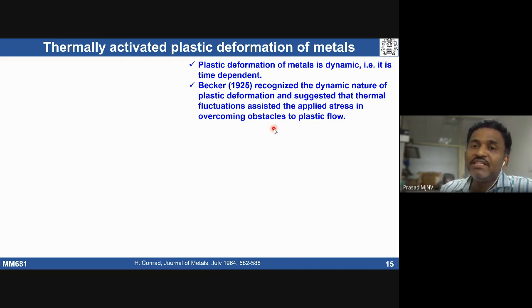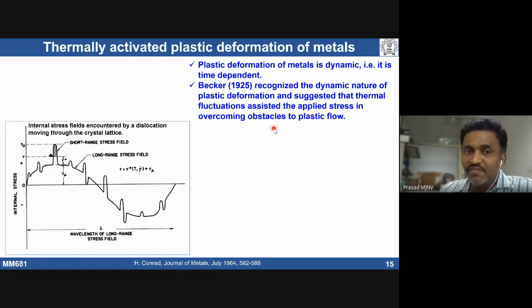These obstacles are of two different types. Some obstacles will have a long range stress field, and some obstacles will have a short range stress field. Assume that I have a crystal, some material, and in that we have some obstacles. Some can have a long range stress field, some a short range stress field. When do you say long range stress field and short range stress field? Long range stress field is related to at least 10 atomic diameters or more.